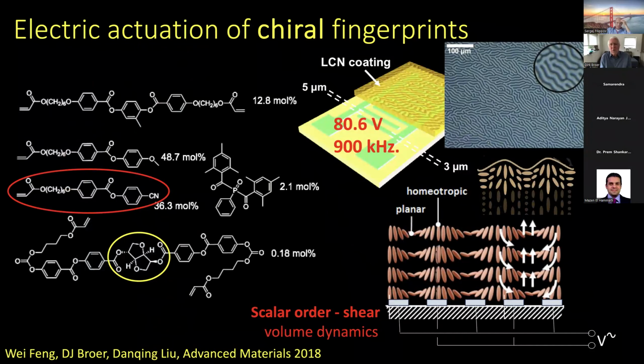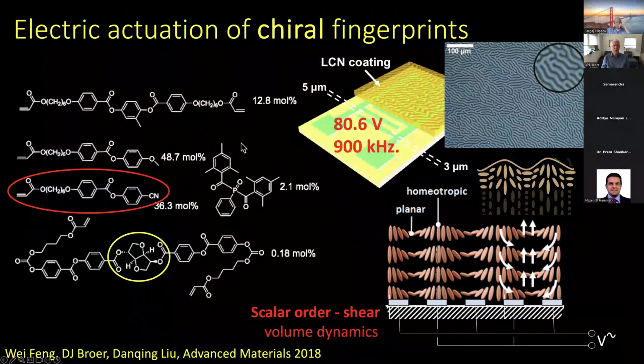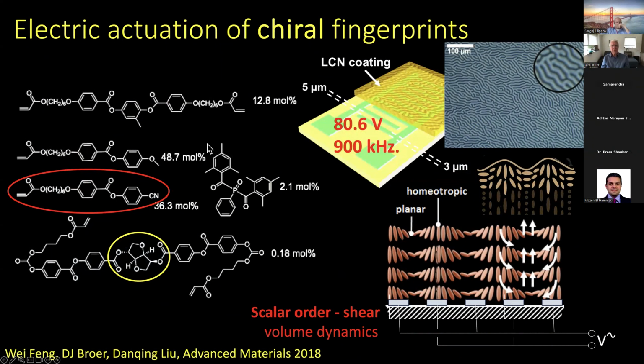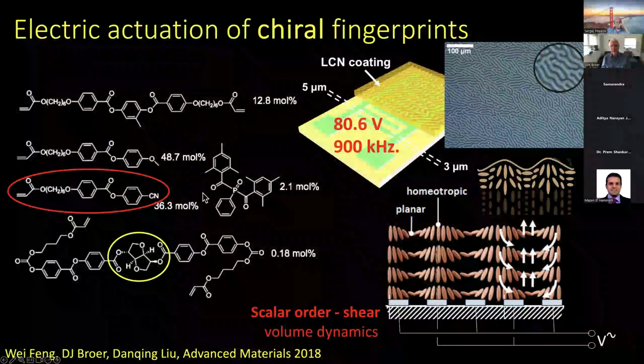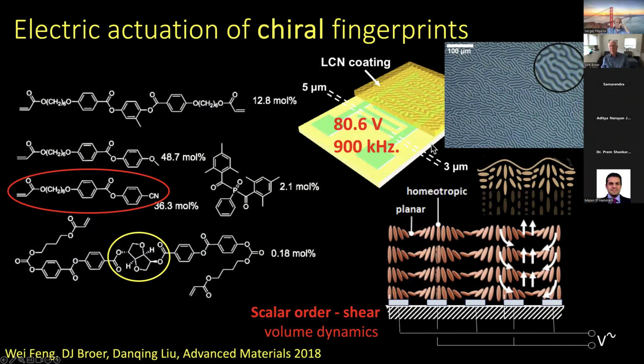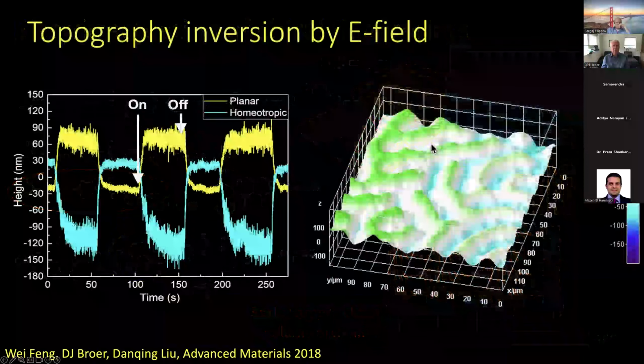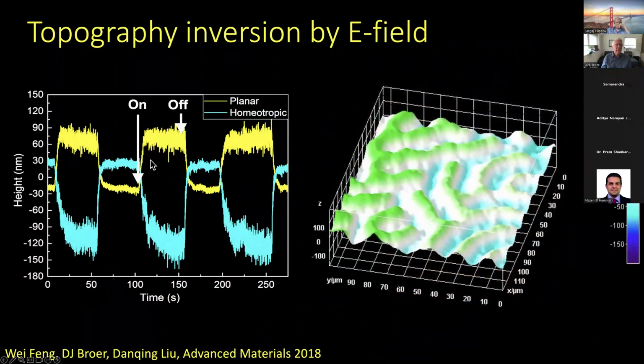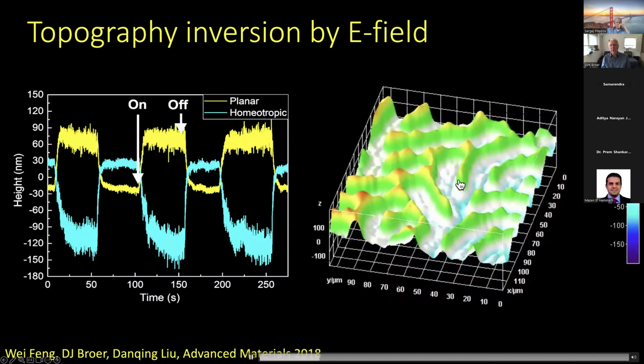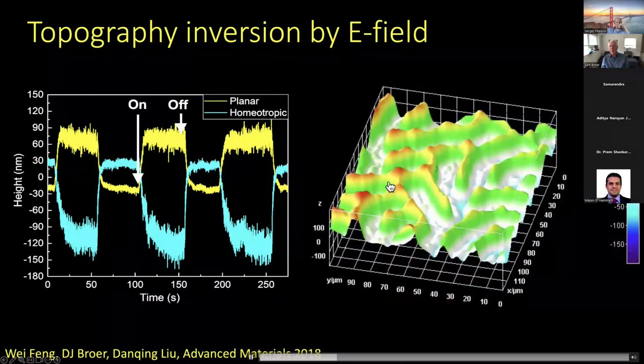So this was electrical actuation of homeotropic films, but the question came whether we can also use this for the cholesteric films, the chiral films, the fingerprints, so to say. So we basically used the same system as we had before. Very important is the presence of this very polar group, which interacts heavily with the electrical field, and then by doing the actuation, we just see the same as we saw with light.